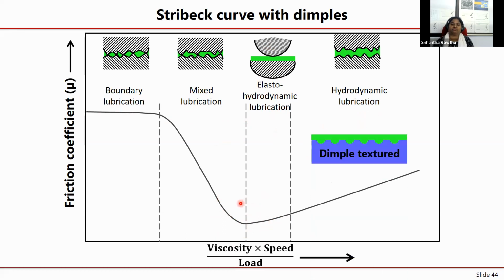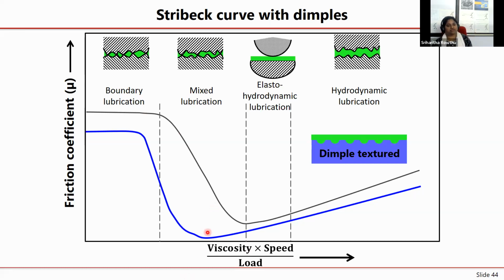We know that if you are creating textures on a surface, then our Stribeck curve shifts downwards as well as leftwards. So if your surface is simply a flat surface with the oil, then that is your black curve. But if you create some sort of micro dimples on the surface, then your friction coefficient value can be reduced even further. That is the concept we wanted to use.